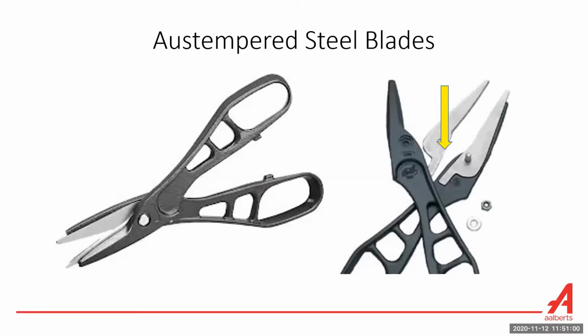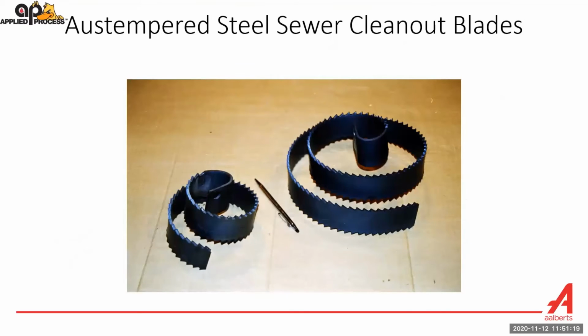This is an interesting product. These are sheet metal shears. The blades are 1075 steel or 1095 steel that has been Austempered. The reason for that is when you're cutting other metals, you don't want the blades to chip, and these will not chip typically. This is a very interesting component as well. These are sewer cleanout blades. These are 1075 steel as well. The reason they Austemper these is, again, because of that high level of stretch before the material breaks. The worst thing that could happen on a sewer cleanout blade is for it to fail when it's doing its job. So they Austemper the steel, and if they hit something that's immovable, the blade simply coils upon itself and does not break.